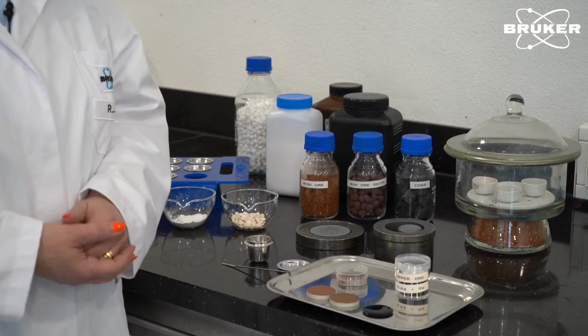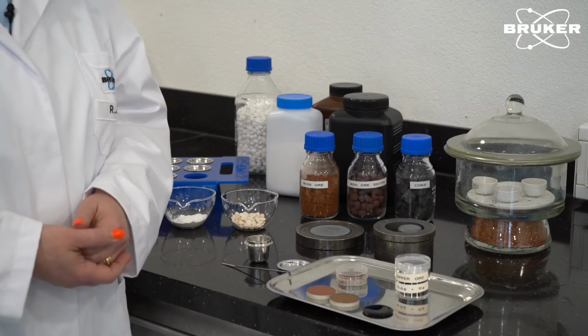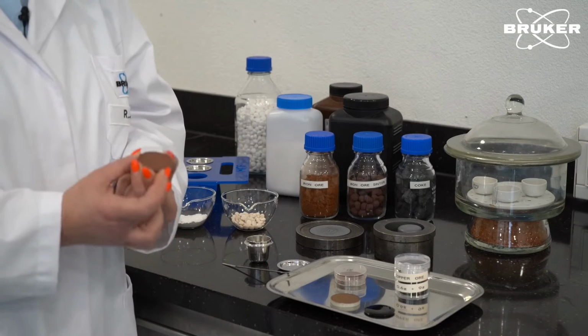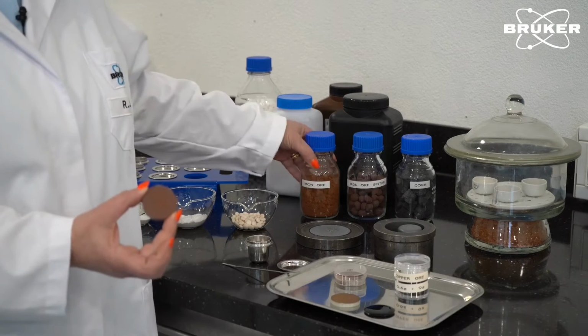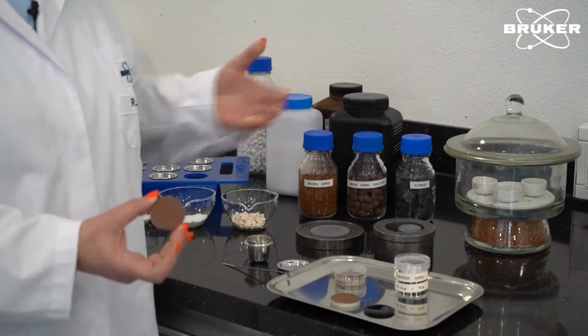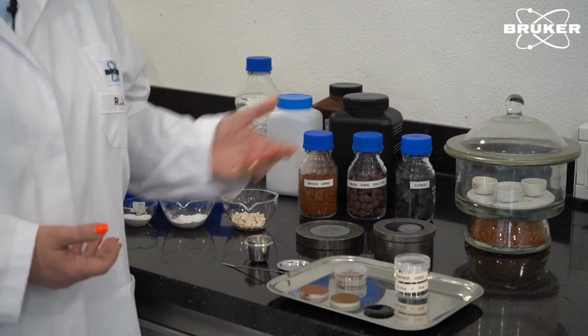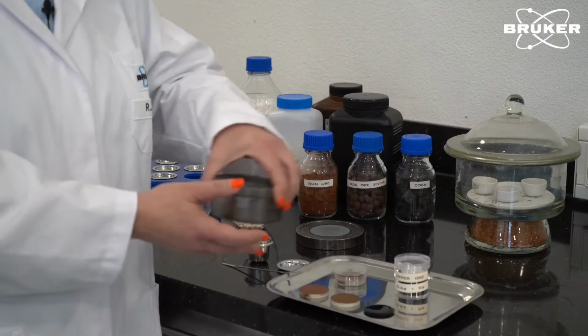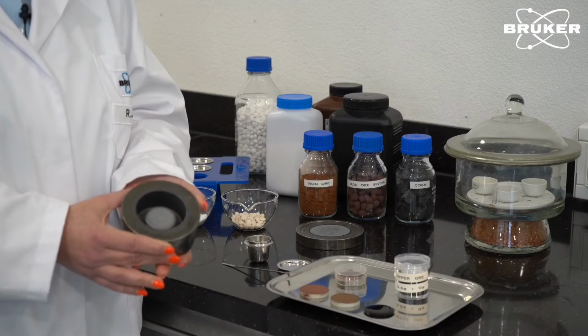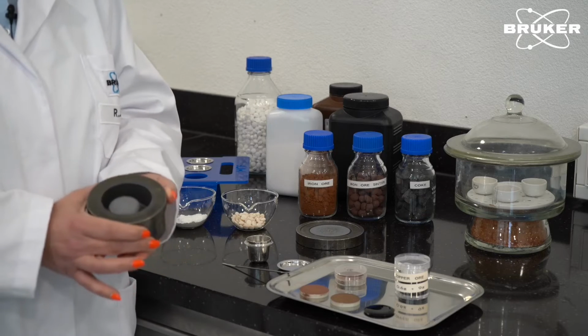Typically in the mining area, let's say the most common prepared samples are fused beads and pressed pellets. Let's start with pressed pellets. Here there is a pressed pellet from an iron ore sample, as you can see it here. So when the samples are coarse, of course you have to grind the samples first. In our lab we use a tungsten carbide vessel, which is of course a small one here, where you can fill maybe about 20 or 30 grams of sample, and you can grind them to get some fine powder, which can be used to prepare the pressed pellets.